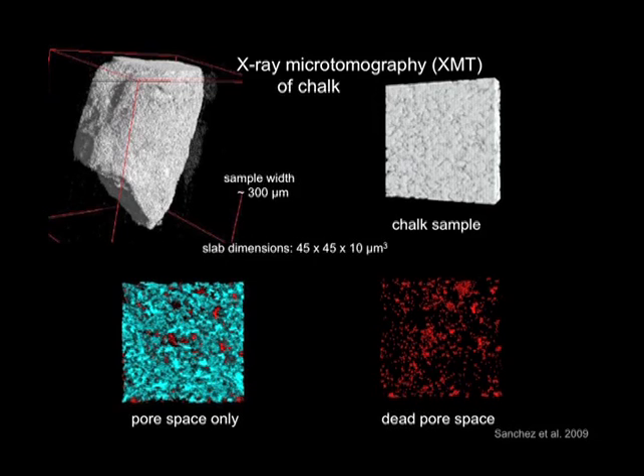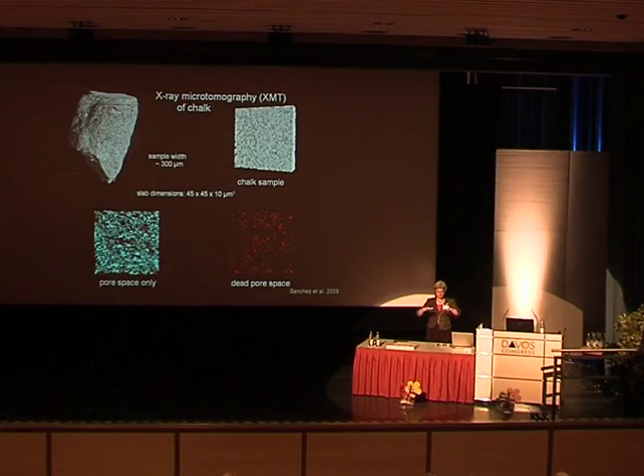Not very big. And with the X-ray microtomography technique, we shine an X-ray beam, usually a synchrotron X-ray, through our sample. And you know when you go to the doctor, you get an X-ray, picture comes out on the back. It's the same with our sample. We shine it through, get a picture, and then we move the X-ray, shine it through again, get another picture, and so on, 1,000 and some times. And then we go down a layer, do it again, down a layer, do it again. We get about a terabyte of data. And then we can use that data to recreate a three-dimensional picture, and then we can take slices wherever we want and get the same on a series of samples so that we can compare one with the next.